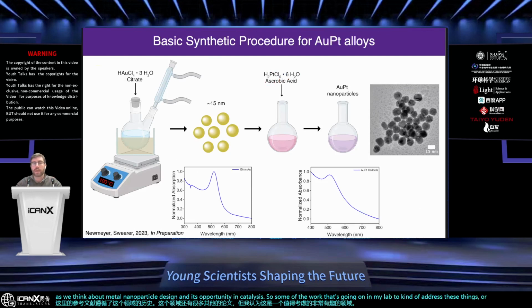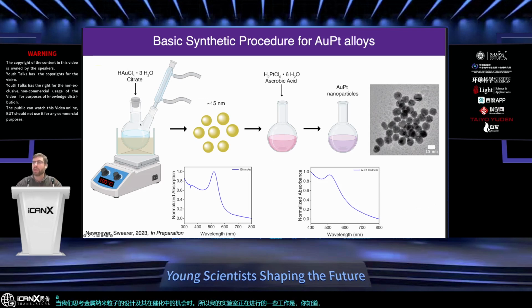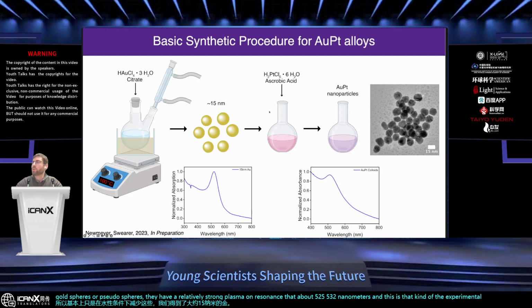basic synthesis of gold platinum alloys. We use a very classic approach that both Matt and Leo know quite a bit more about than I do. We're taking chloroauric acid and citrate. We're doing a temperature reduction, so basically just reducing these in aqueous conditions. We get about 15 nanometer gold spheres or pseudospheres. They have a relatively strong plasmon resonance at about 525, 532 nanometers, and this is the experimental spectrum that we've collected. And then what we do is we inject